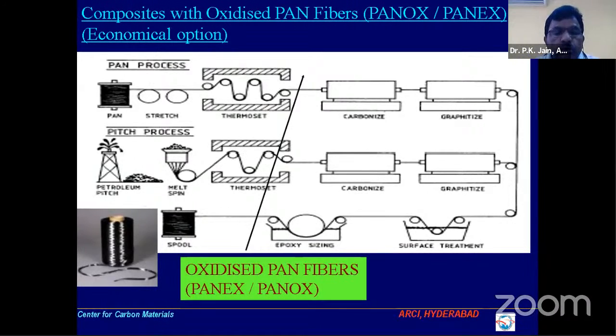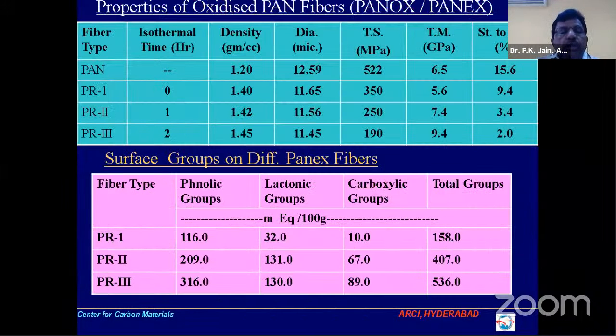Another study, as I told you, some efforts we made for economical purposes, because these composites were carbonized and graphitized separately, and we took a carbon fiber which is already pre-carbonized and graphitized. We thought, if we take the fiber at this stage, which we call the pre-carbonized stage, and then develop a composite, and then try to see whether the in situ carbonization and graphitization of this along with the fiber can save some money, the processing money. So the idea was very interesting, and we have given the nomenclature: PAN, PR1, PR2, PR3.